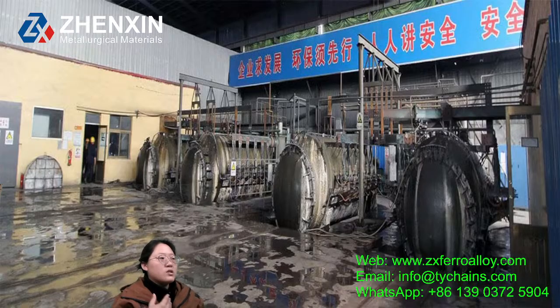You are not just buying the Ferronickel, you are buying the nickel units and the process compatibility. For example, there are two suppliers both for Ferronickel 20, but one has a higher silicon, which may affect the slag, and one has the higher carbon, which will affect steel chemistry. So when you plan to purchase the Ferronickel, always check the full composition and not just the nickel content.